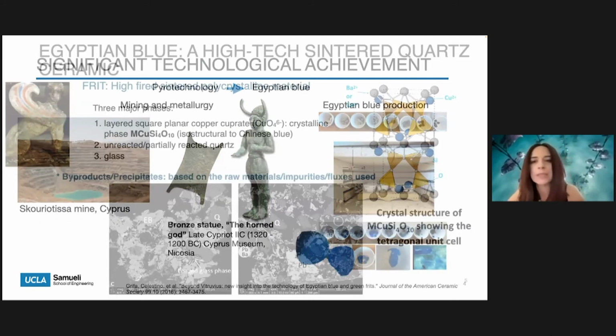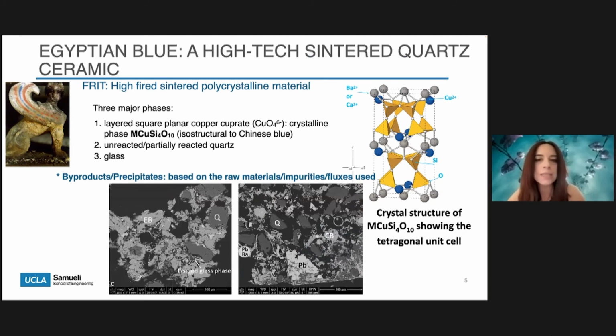From a materials perspective, Egyptian blue is considered a high-tech sintered quartz ceramic, as many colleagues also mentioned earlier today. It represents a notable example of a synthetic high-fired sintered polycrystalline material known as frit, with three major phases: a crystalline phase containing this layered square planar copper cuprate, also the isostructural part with Chinese blue, unreacted quartz, and glass. You can see in these images here the three main phases in Hellenistic Egyptian blue and its contemporary handmade counterpart.